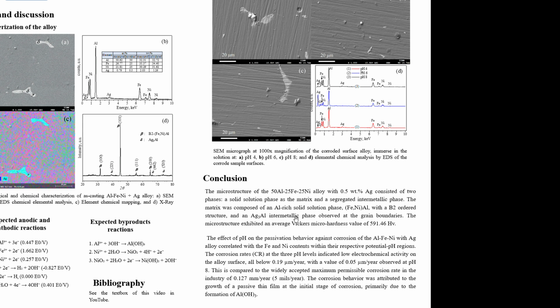The effect of pH on the passivation behavior against corrosion of the aluminum, iron, nickel with silver alloy correlates with iron and nickel contents within their respective potential-pH region. The corrosion rate at the 3 pH levels indicates low electrochemical activity on the alloy surface, all below 0.19 micrometers per year, with a value of 0.05 micrometers per year observed at pH 8. This compares to the widely accepted maximum permissible corrosion rate in the industry of 0.127 millimeters per year.